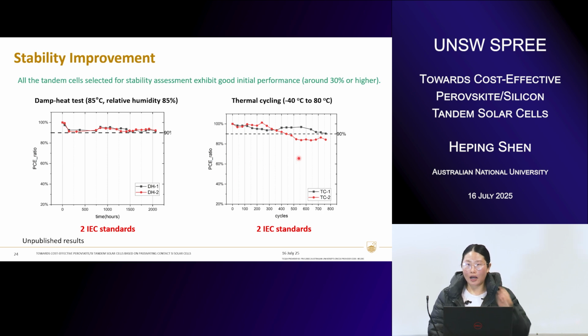We took some of the highly efficient tandem cells, which usually have an initial efficiency above 30%, and then we encapsulated them using optimized encapsulation, incorporating both edge sealing and full-area sealing, that more or less mimics what is used for commercial silicon cells, but with some modification of the material and process. We tested first against the IEC standards that are set up for silicon, and we found some of these cells show very promising stability because of our encapsulation as well as our cell optimization.